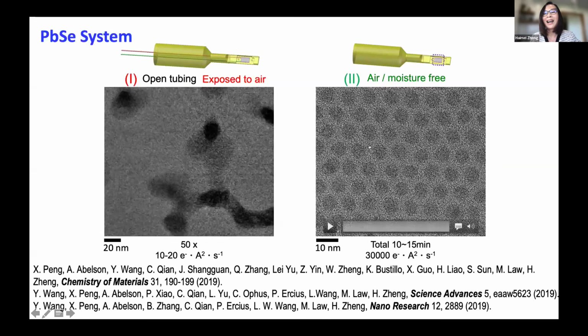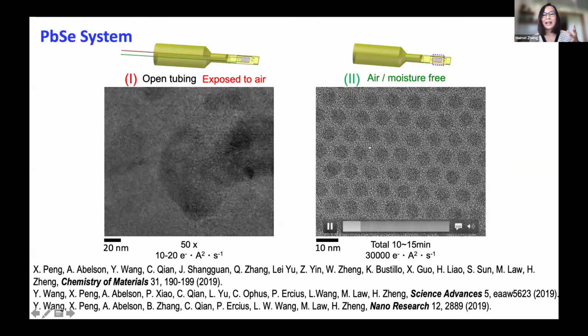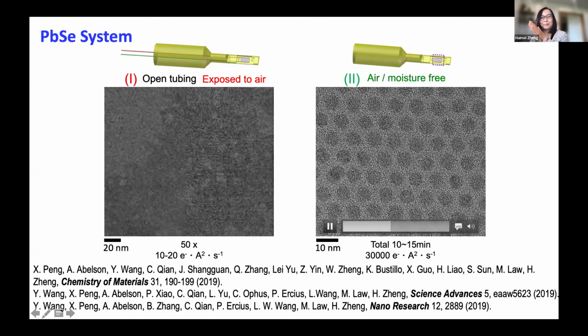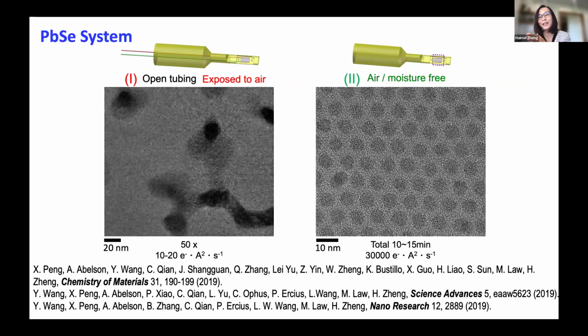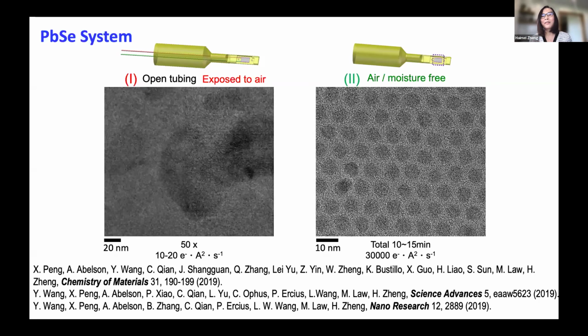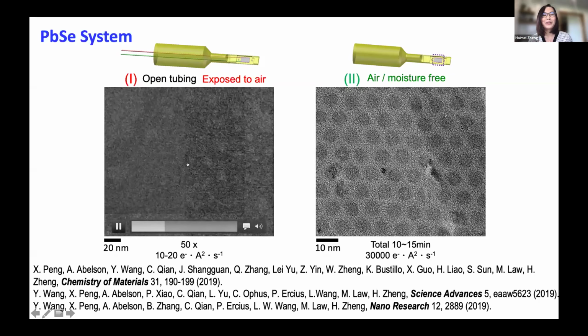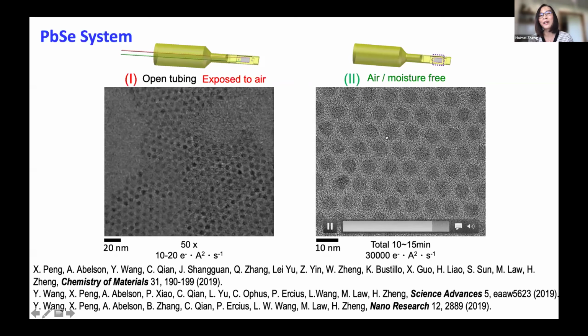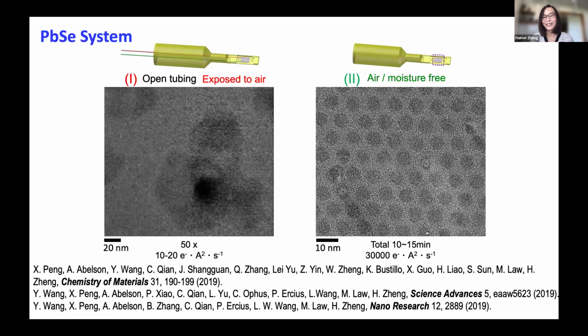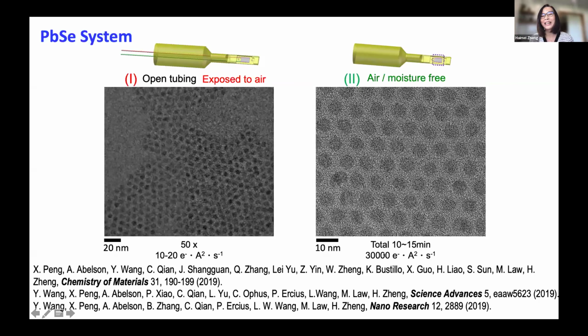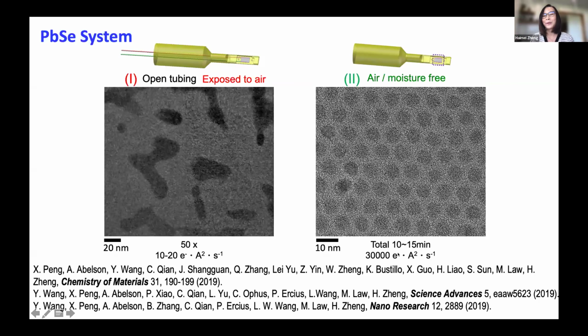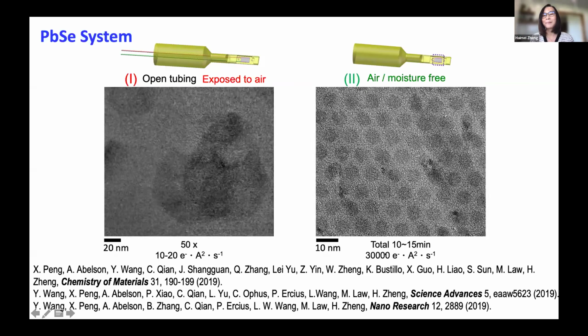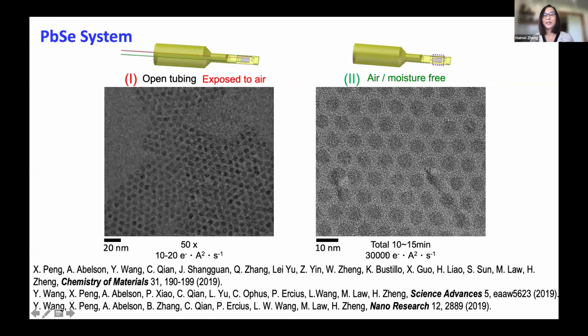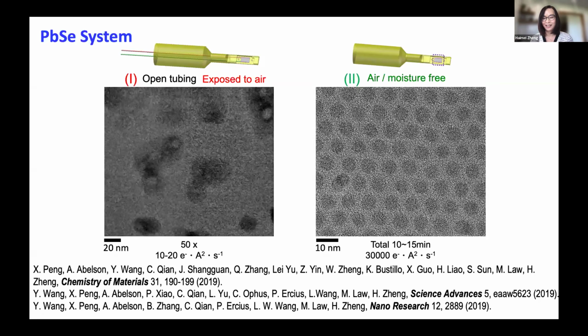And we looked at it slightly open to the air, and we also see it dissolve. However, we assembled this nanoparticle in a glove box and sealed it. And we found that without exposure to moisture and oxygen, the tolerance dose in the liquid can be much higher, up to 30,000 electrons per angstrom square per second. This is a very high electron dose threshold.